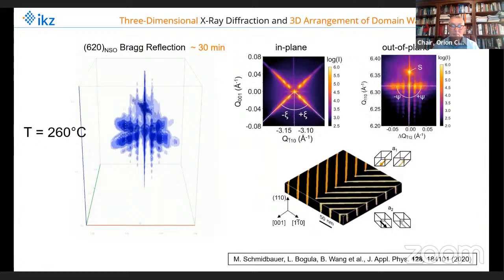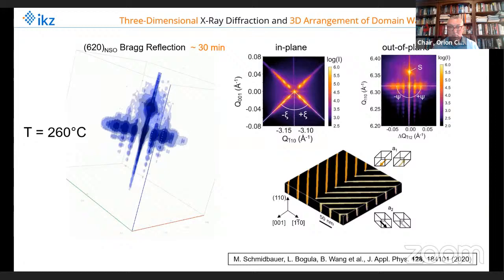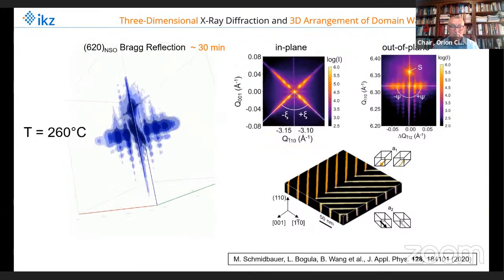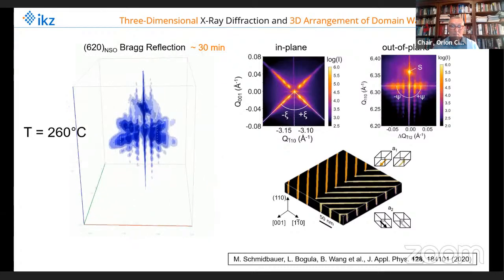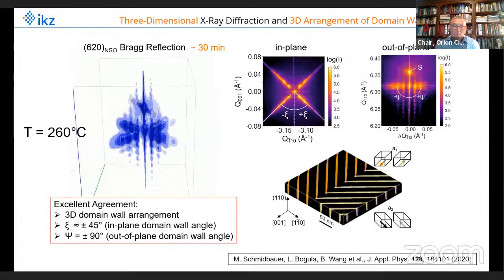You can do the same thing now for the high temperature phase. Again, you see a very rich diffraction pattern, and you can do again in-plane and out-of-plane sections. In the in-plane section, you see a cross-like behavior, and this cross comes from the stripe domain patterns, which are oriented 90 degrees to each other. So the angle Xi is plus minus 45 degrees. More importantly, when you look at the out-of-plane section, you see the intensity distribution aligned in the horizontal direction, proving that the domain walls are oriented vertically to the sample surface, and this is exactly what you observe in the phase field simulation shown below. So again, a very, very good agreement between theory and experiment.